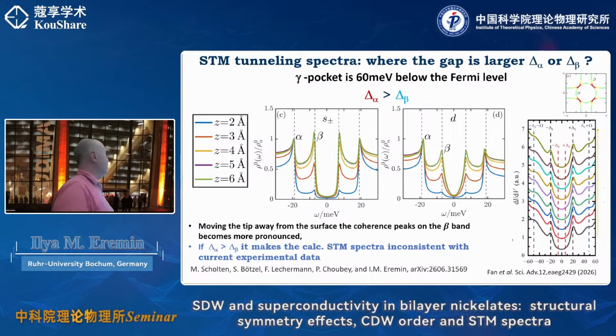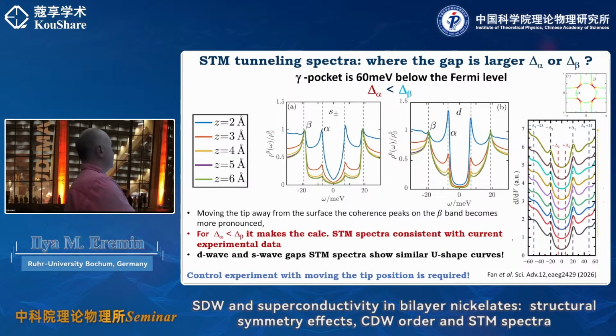And indeed, if you do this calculation, if you assume that the larger gap is sitting on the beta pocket, which has a lot of contribution from the z-square, then when you come to a reasonable value of the height, like 5-6 angstroms, this more or less corresponds to the experimental situation. You see that indeed your data start to be much closer to the experimental situation.